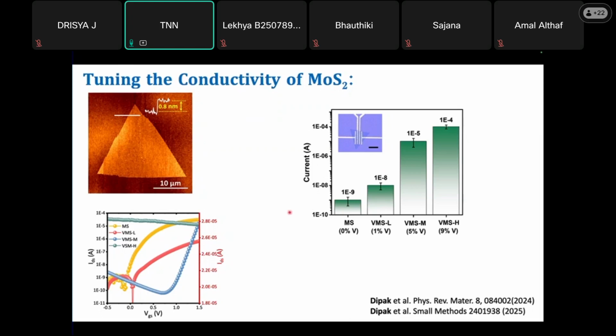Now we are looking for a semiconductor which is stable at that temperature. At the same time, it is semi-metallic, and it forms a nice van der Waals junction between the metal and the semiconductor. Right now, we are looking for such a material, and we found that you can actually tune the conductivity of MoS2. MoS2, as I mentioned, is a semiconductor, but we found that we can control its electronic conductivity by doping with certain elements like vanadium.